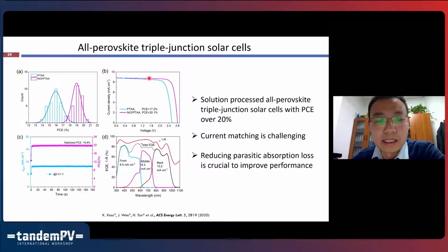But from the EQE spectrum, we can see that for the three subcells, the current matching is not easy. So it is still quite a challenge to get a current matching condition. And also, due to the introduction of several more charge transport layers, the optical losses are higher than in the tandem devices.